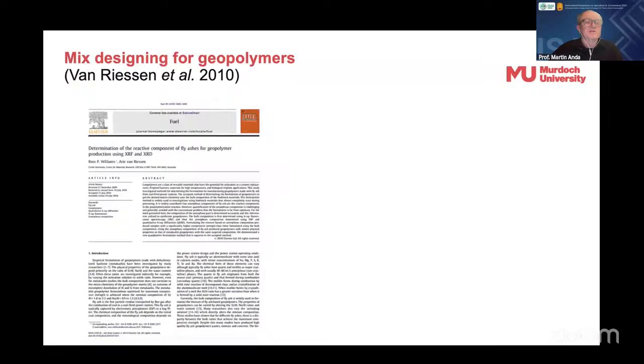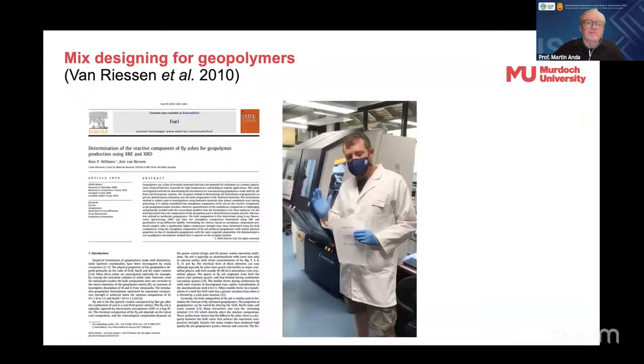If we look at some of the other research that's occurred in Western Australia by Professor Van Riessen, he produced with his PhD students some very useful papers on how we can develop a procedure for having the mix design for geopolymers using X-ray fluorescence machine and X-ray diffraction machine. And so this gives us the data that we need in order to prepare the mix design for a geopolymer. And luckily at Murdoch University, we also have a very good XRD machine, a Rigaku unit from Japan. And there's Dr. Hans Oskieski, who's in charge of that machine, and we're able to use that to do some of our mix design work for preparing these geopolymers.